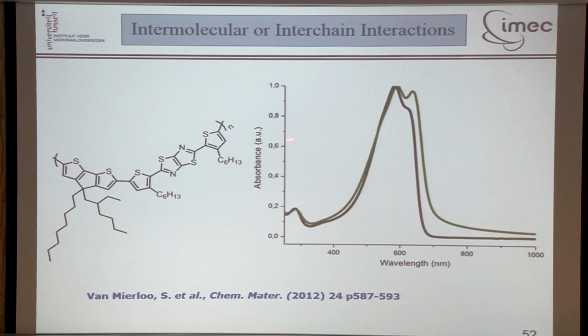In the polymers themselves, you can also see that effect because of packing, mostly with a crystalline structure. You bring the chains closer to each other, so there's a component of two-dimensionality, and so you see a shift. This is the spectrum in solution, so chains don't interact.